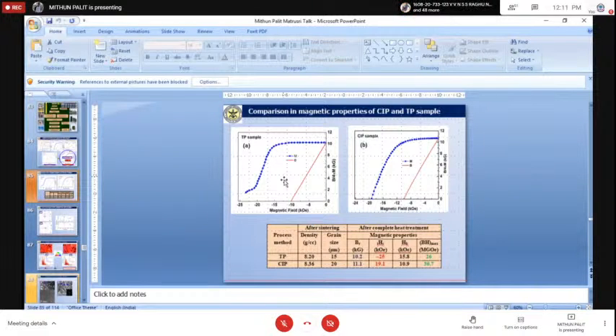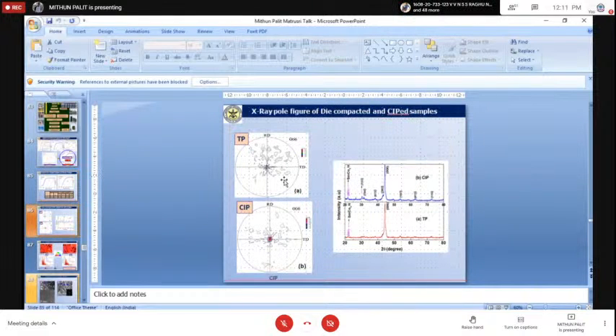So we wanted to investigate what the reason is. Again, we have resorted to the X-ray pole figure technique. You can see the cold isostatically pressed, that is called the CIP sample. The orientations are very tightly spread around the origin, so therefore it has more orientation. If you connect this fact with the equation I showed before, stronger orientation means you have a stronger magnet, stronger Br. Accordingly, the CIP sample has more Br.